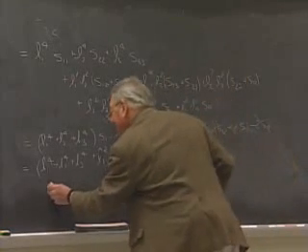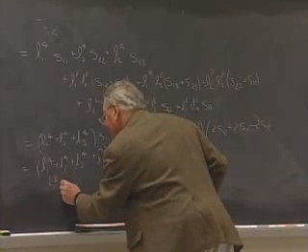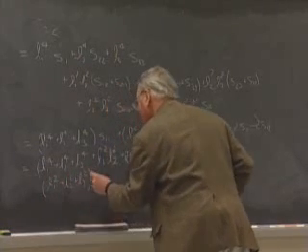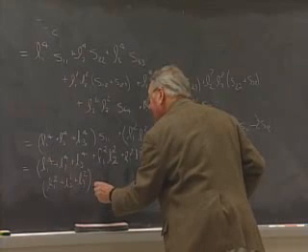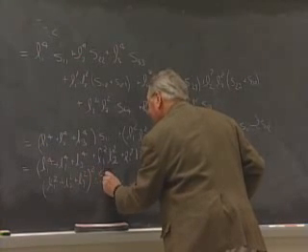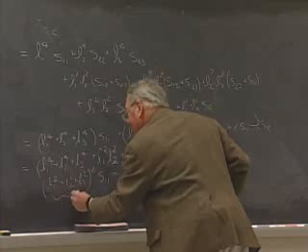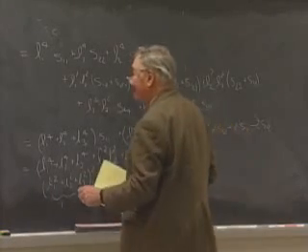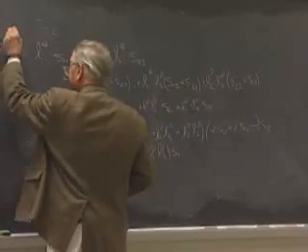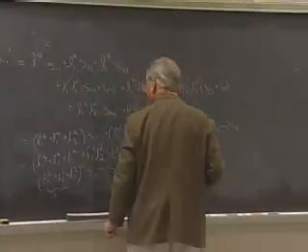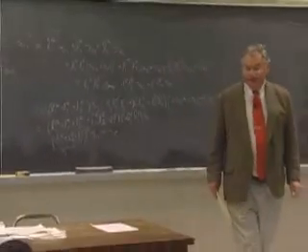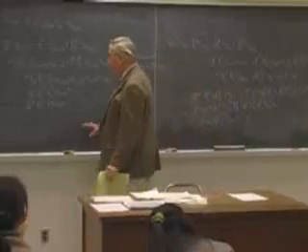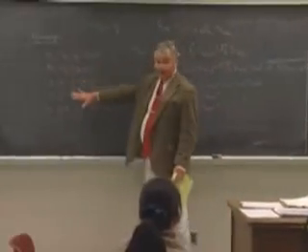But this turns out to be equal to simply L1 squared plus L2 squared plus L3 squared, the sum of the squares of the direction cosines of our rod, quantity squared, times S11. And this term inside the parentheses is 1. So indeed, S11 prime is equal to S11. So the value of Young's modulus has not changed with direction if the form of the compliance tensor is like so.